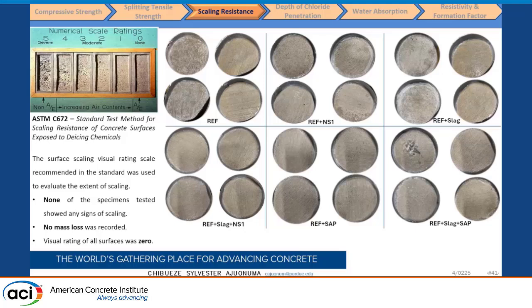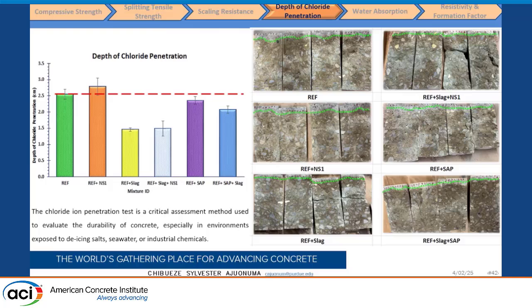Then, moving forward, we look at some of the results from the durability tests. For the scaling resistance at the end of 50 cycles using visual inspection, we found that there was no mass loss, and the visual rating was 0 for the slabs. And for the depth of chloride penetration, at the end of the application of silver nitrate on the cores, we noticed the addition of SAP and 30% slag replacement helps to refine the microstructure, leading to a reduction in the depth of chloride penetration. SAP introduced a kind of voids in the mix, but the addition of SAP and slag also helped to refine the microstructure, reducing the depth of chloride penetration for the mixes.